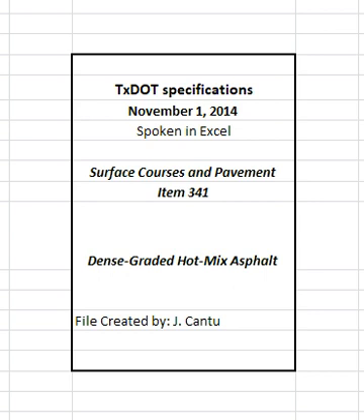4.9.3.3.1 In-place air voids. The engineer will measure in-place air voids in accordance with Tex-207-F and Tex-227-F. Before drying to a constant weight, cores may be pre-dried using a CoreDry or similar vacuum device to remove excess moisture. The engineer will average the values obtained for all sublots in the production lot to determine the theoretical maximum specific gravity. The engineer will use the average air void content for in-place air voids.